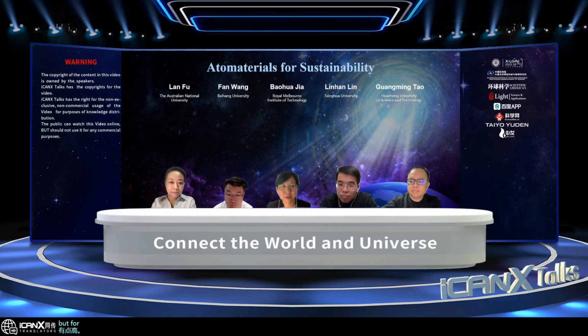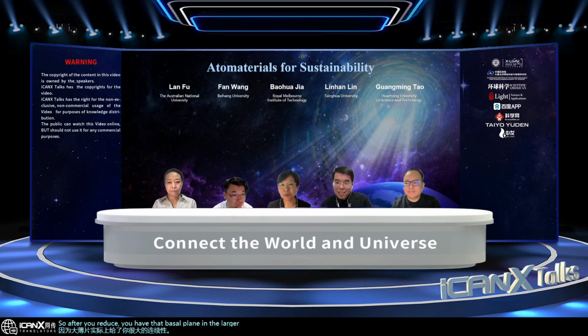But for electronic property, large flakes actually give you large continuity. So after you reduce, you have that basal plane in a larger scale. Therefore, the conductivity will be better. So these are quite dependent on your application. But we found that normally it's on the order of 1 micrometer. So the flake size, smaller or larger, that's the kind of middle line.